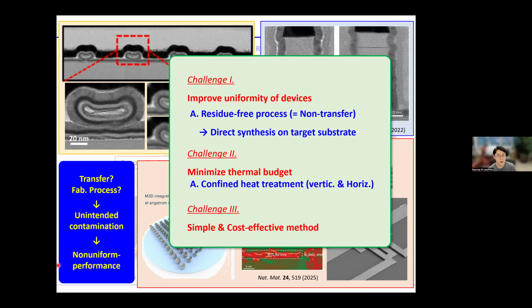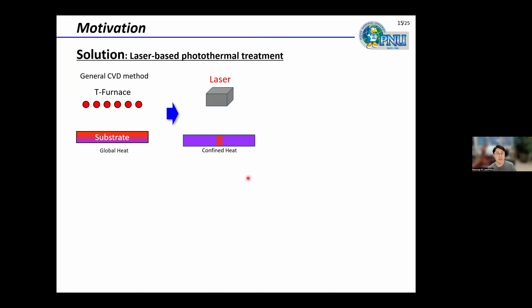Interestingly, we already have the direction of solving these challenges. To improve the uniformity, we need the residue-free process, meaning the direct synthesis of nanomaterials on the target substrate. And to minimize the thermal budget, heat energy should be applied in some confined area. Maybe it is not perfect, but we propose a solution based on laser-driven thermal treatment.